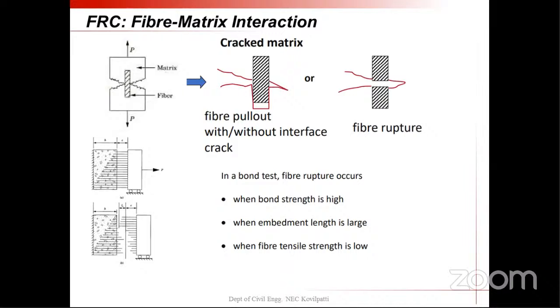And when you're dealing with toughness characterization, you should know two things, that is, what is the fiber matrix interaction? Because fibers bridging across the cracks will transfer the stress through the cracks, from one point to the other point. So in the cracked matrix, in the left figure, one element is subjected to tensile stress, and a crack has been formed, and the fiber is bridging across the crack. So these fibers are essential in transferring the stress from one point to the other point. And due to the transfer, sometimes fiber pull-out may occur. But if the fiber is not able to withstand that stress, the failure may take place by two mechanisms, either a fiber pull-out mechanism or a fiber rupture mechanism. So during my experimental investigation, I observed all the specimens underwent the fiber pull-out mechanism, because fiber rupture can occur only at high tensile stresses.